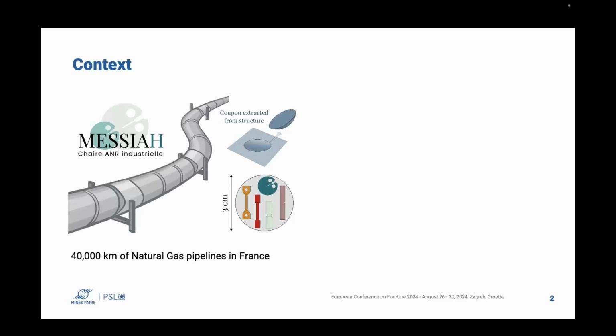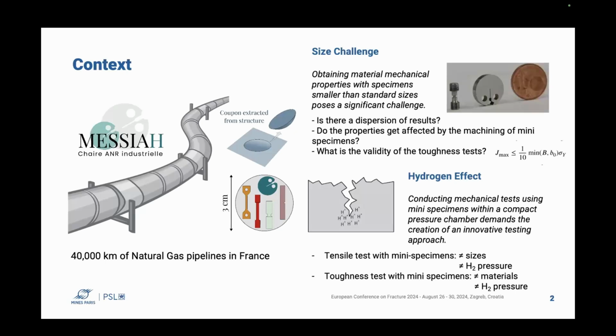It proposed to take a small coupon of the material directly from the structure of the pipeline without the need to interrupt the production. And from these small coupons, machine mini specimens that will permit us to characterize the mechanical properties of the pipeline. But when we talk about mini specimens, or small size specimens, we have some issues that are related to the size of the specimens. First is the machining. As the specimen is very small, it could have some effect of machining, because of the induction of residual stress, for example.